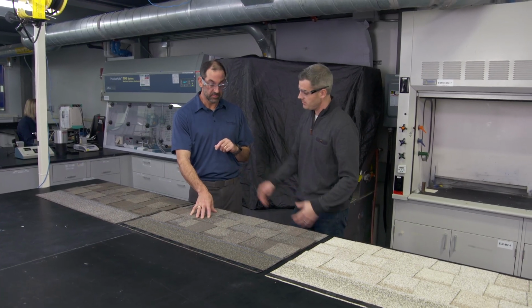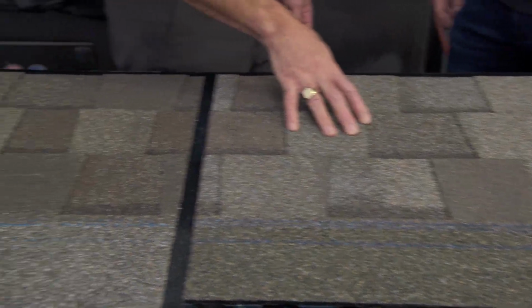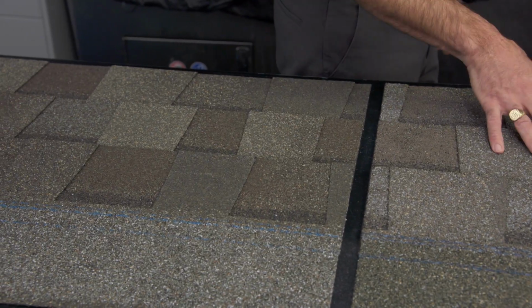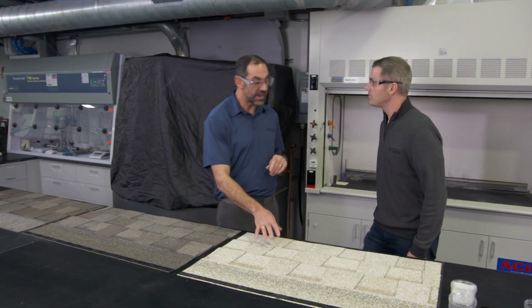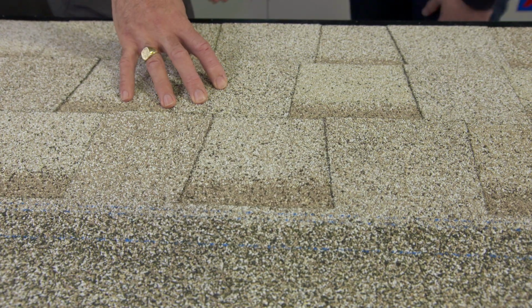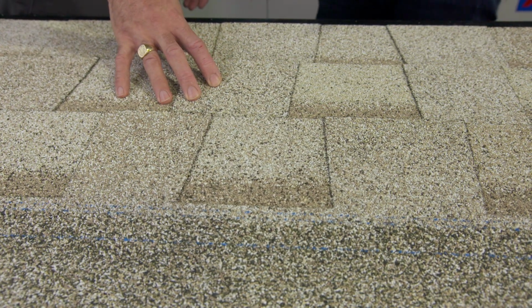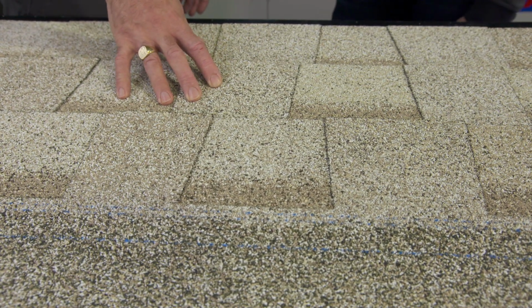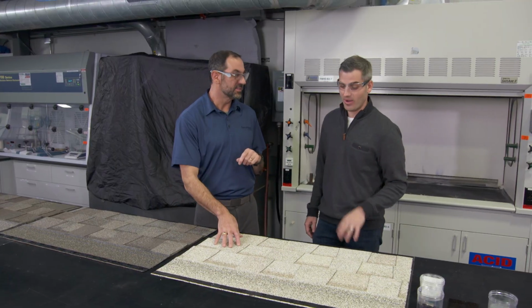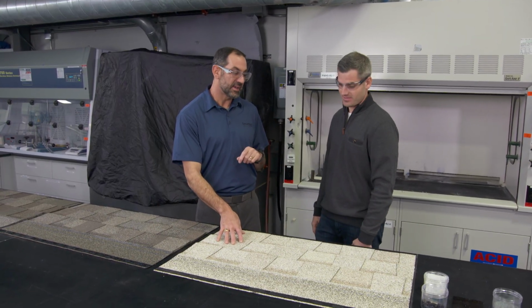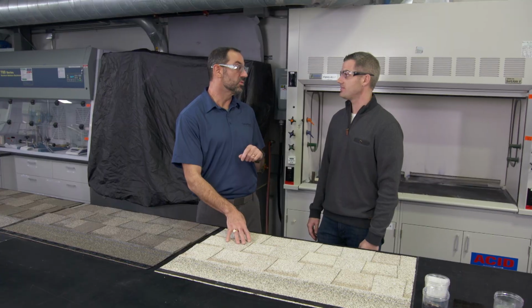Okay, and it looks the same. Yes, actually we're able to get that solar reflectivity while maintaining these dark colors. Then we can take that one step further and use a lighter material blend, but also a specially formulated granule to take that to a solar reflectivity of 40%. So double that. Double that. Wow, and definitely visually very different. Yes, and again, a dramatic impact on the cooling of the roof.